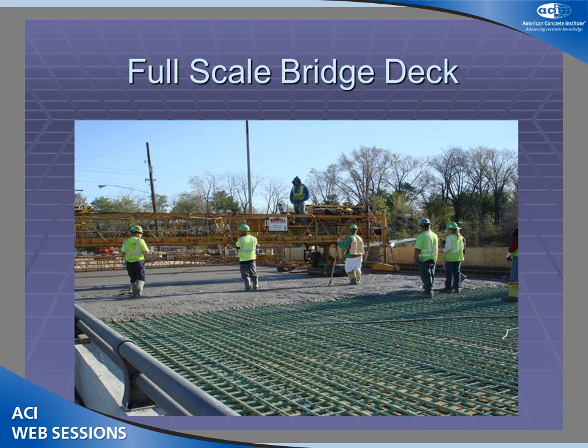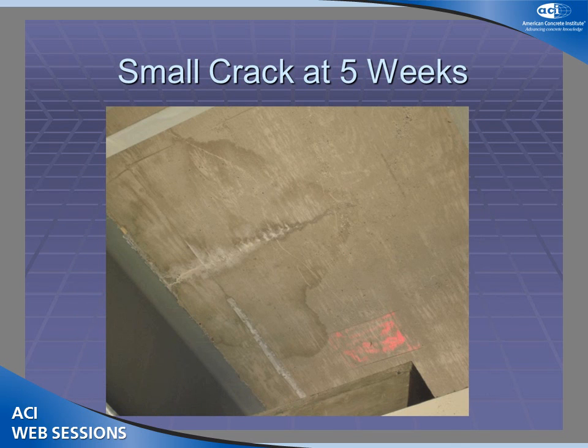So those are some pictures we took in the casting of the full-scale bridge deck. And then we had a small crack. We think there may be a small crack that showed up at about 5 weeks, but it could almost be an artifact of the light. So Dale and I put in the abstract for this, and then we realized at some point that, wait, the paper's due. Maybe we should go out and take another look at the bridge.